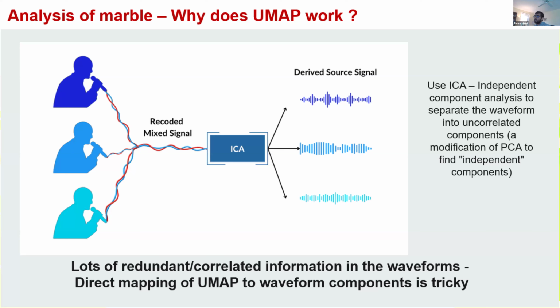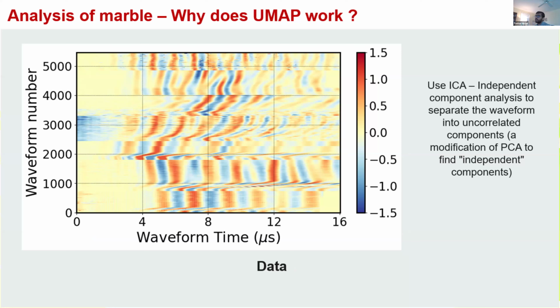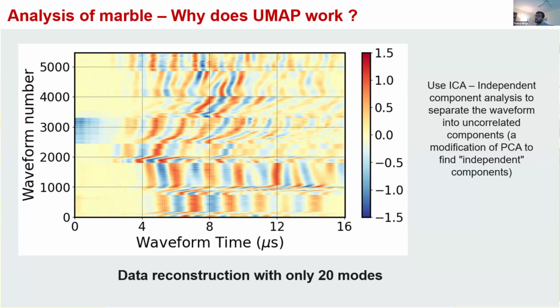So within the context of our analysis, ICA was really useful in taking the waveforms and reducing it to a smaller subset of independent components, asking whether they could be even reduced to smaller subcomponents, and then using those to understand what UMAP is doing to reduce the dimensions further. So we start with data like this, which is all the waveform data, all of the experiments combined together. And if we only use 20 modes across all this experimental data set, we can reproduce the full waveform information almost exactly.